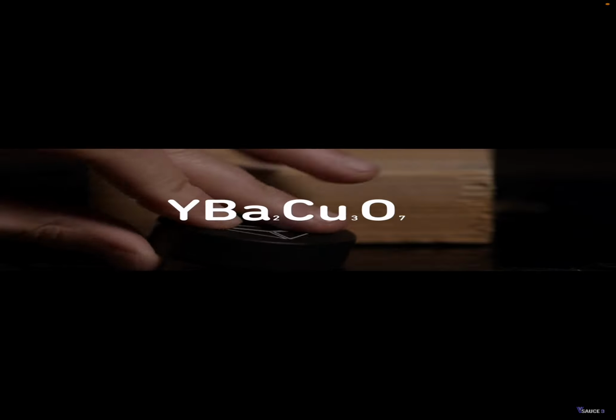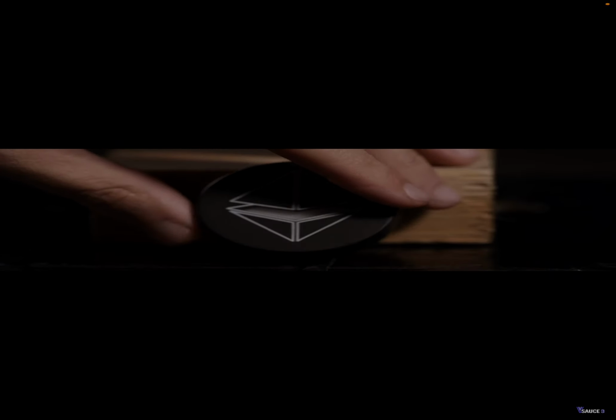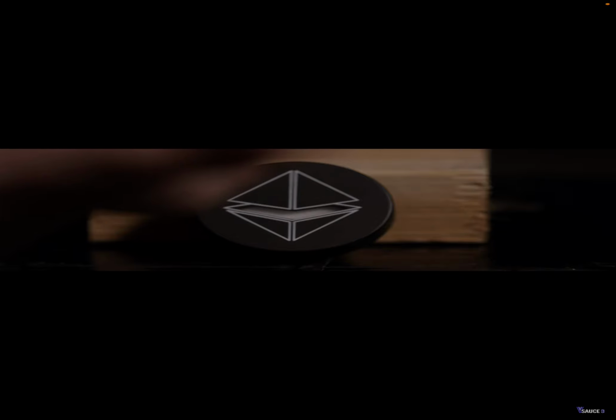not magnetic. Now, this is our superconductor, a small disk made of yttrium, barium, copper oxide. Actually, in this whole thing, the superconducting material is just a tiny sliver of crystal grown on top of a stainless steel core and covered by a protective layer of silver and aluminum. And when I say a tiny sliver, it really is. It's just 3 microns thick, 30 times smaller than the thickness of a human hair. And if I were to put a magnet next to it, well, nothing happens because it will only levitate when it's below that critical temperature, which is why I drowned it in liquid nitrogen.